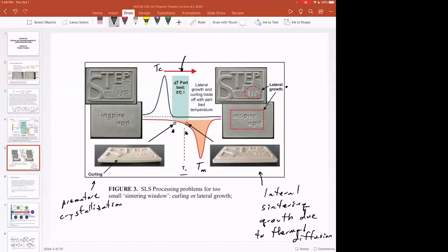And if you're getting premature crystallization, that means you're too close to TC. And so you're getting crystals or a densification, let's say. And curling. So anytime you see this curling or warping, it's usually because you have some sort of densification process or too much of a thermal gradient, and you can see that that part curls up, and that's very bad news when you start to think about the operation of a powder bed and spreading powder over that curled part.